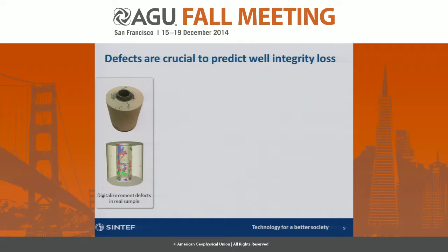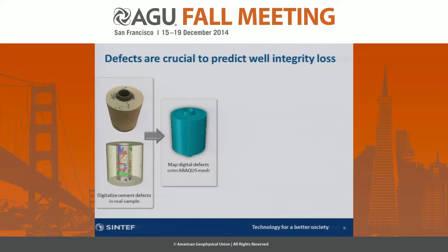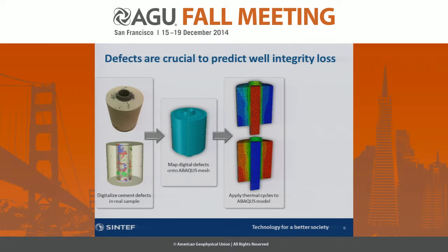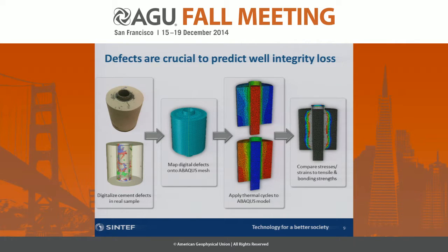And then what we are doing is to use these samples to actually, again, put them into Abaqus. So map the defects, the digital defects from CT onto the Abaqus mesh, and then expose the sample to temperature variations, the same temperature variations that we have in the laboratory. And then we get a completely different picture of the stresses building up in the sample.